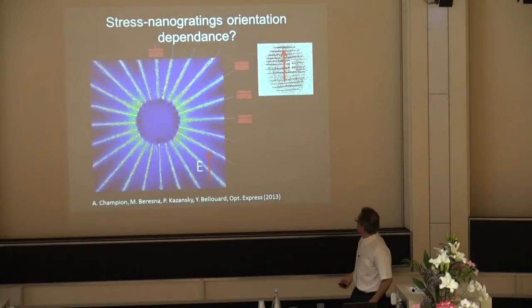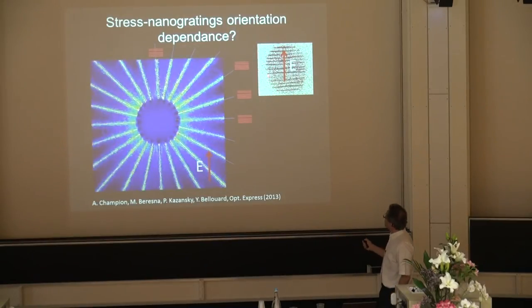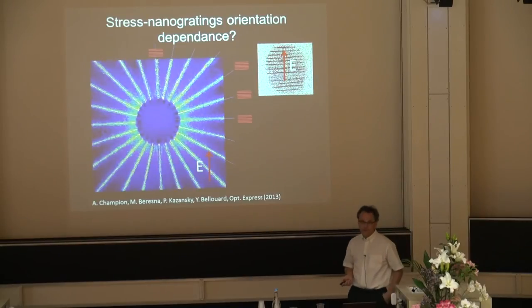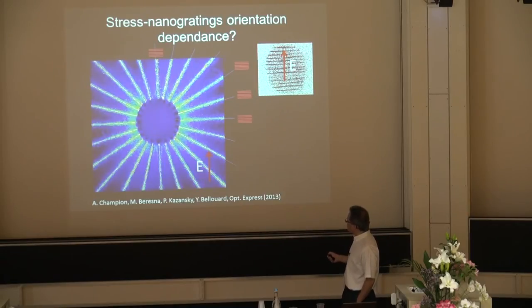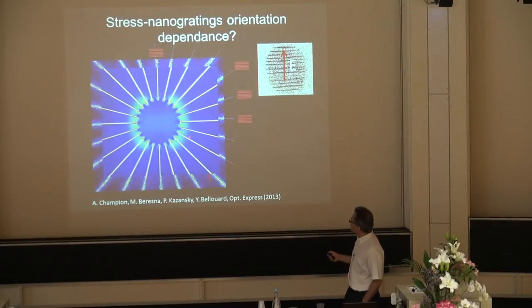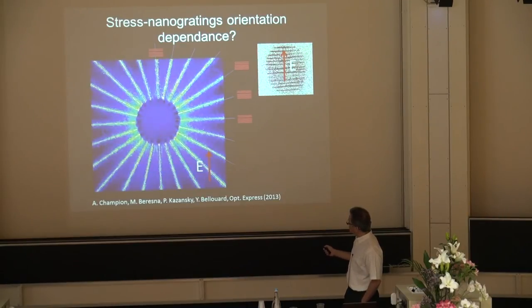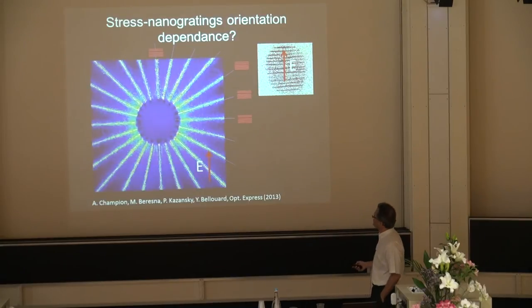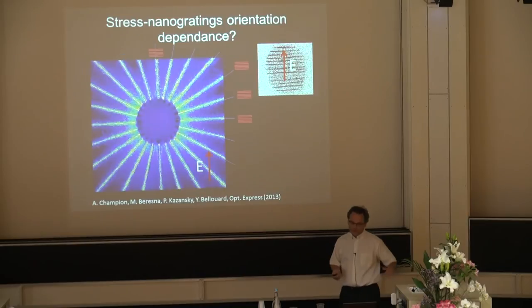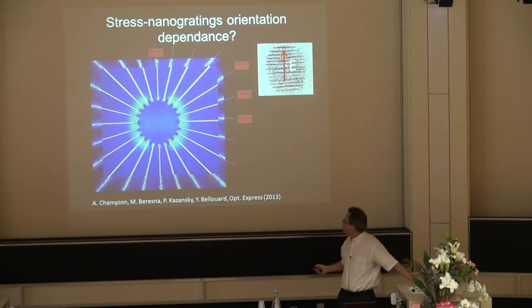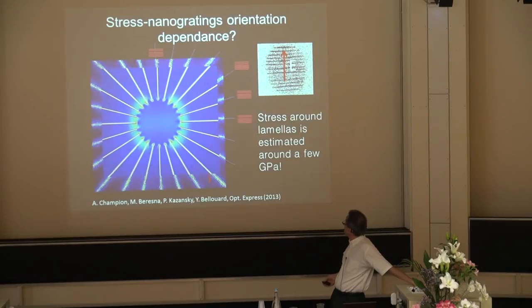Very fascinating. And as I mentioned, this nanostructure, imagine this is one laser spot, so this is microns. The orientation of those planes depends on the electrical field, so the polarization of the laser beam. So now you can imagine if I write lines and I don't change the orientation of the electric field, then my nanoplanes are always oriented the same, like this. But obviously, this has a different effect on the material, in particular in the different region between the lines. That indicates that you put some stress in the material, but it will depend a bit on the orientation of the nanogratings.